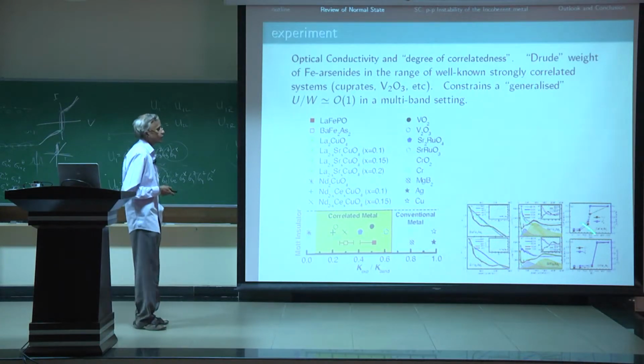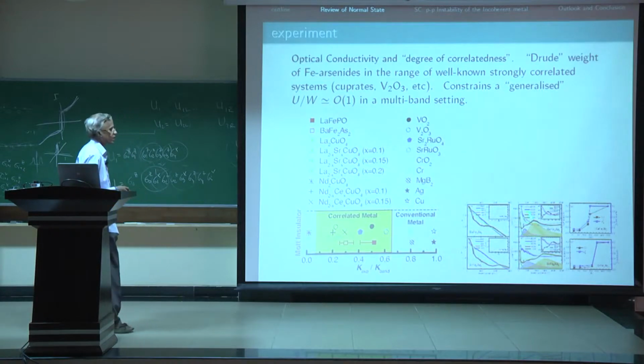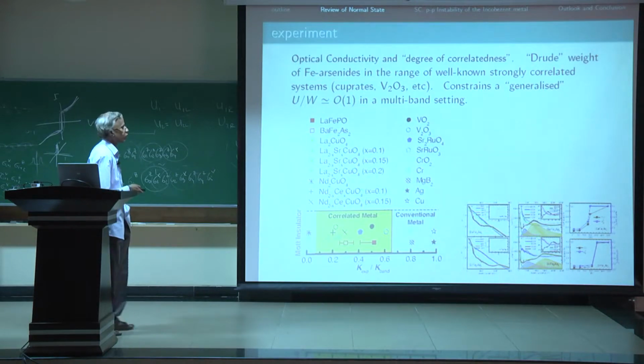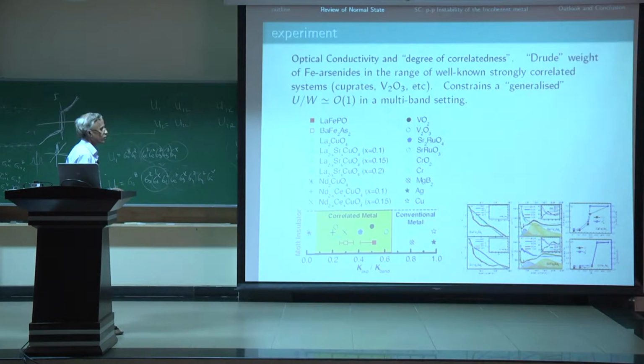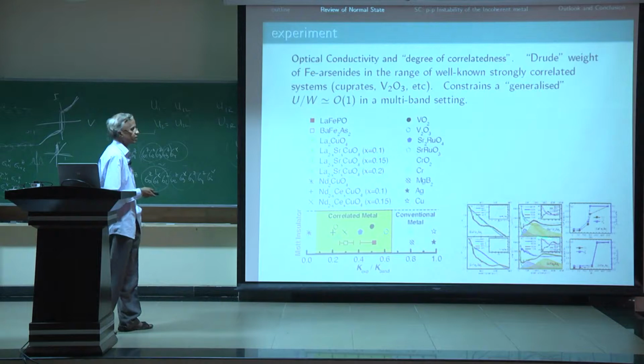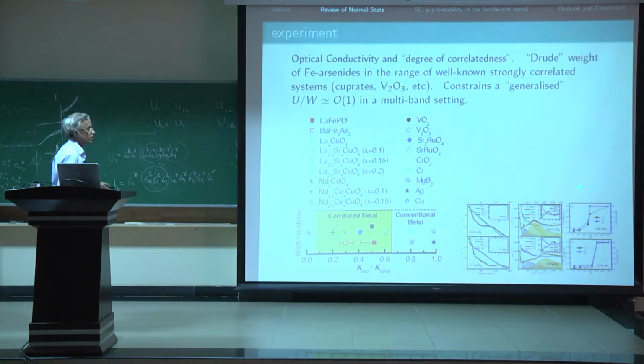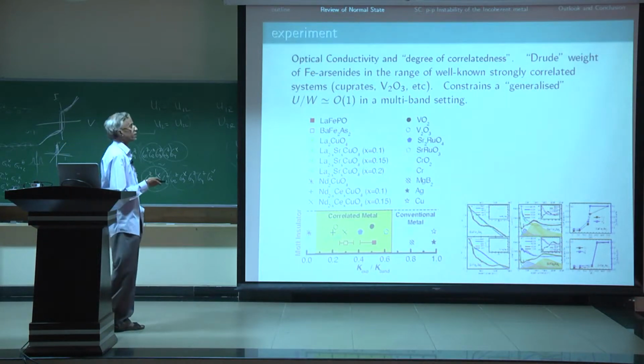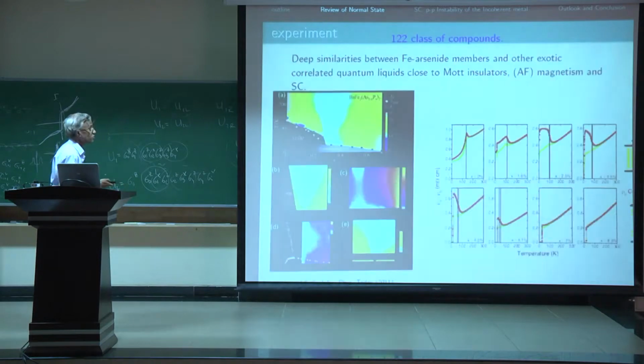That is actually also seen from the direct optical conductivity data, wherein a very small coherent component sets in subsequent to the structural distortion and in the antiferromagnetically ordered phase. But if you go above in the normal state, without any symmetry breaking, the optical conductivity is very broad, and it's difficult to discern any long-lived quasi-particles from the kind of optical conductivity that is seen. Okay?